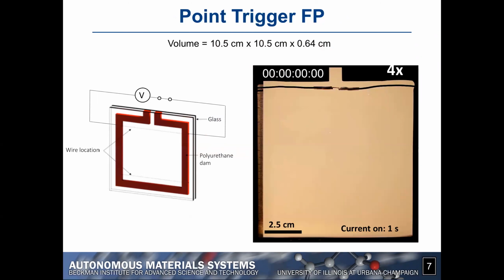So we have a relatively small amount of dicyclopentadiene, which is in the liquid form originally, right? So it has more or less the viscosity of water. And we introduce a small amount of heat in the form of joule heating associated with the current that passes through the wire embedded on the top. So we introduce it just for a little bit, and then we just let the front propagate.